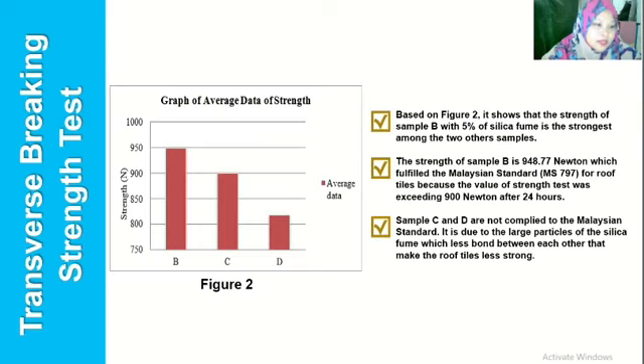Let's proceed to the next test, which is the transverse breaking strength test. Okay, the figure shown here shows that the strength of sample B with 5% silica fume is the strongest among the other 2 samples. The strength of sample B is 948.77 Newton, which fulfills the Malaysian standard MS 797 for roof tiles because the value of the strength test exceeded 900 Newton after 24 hours.